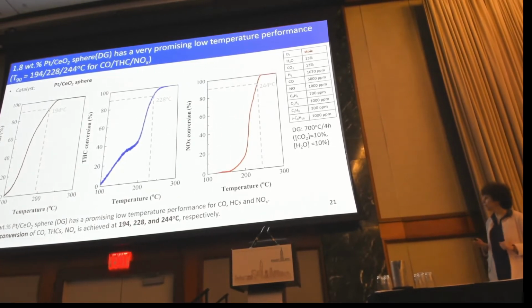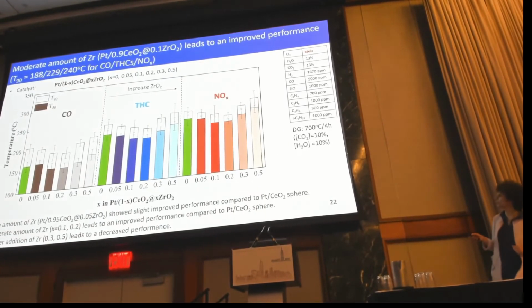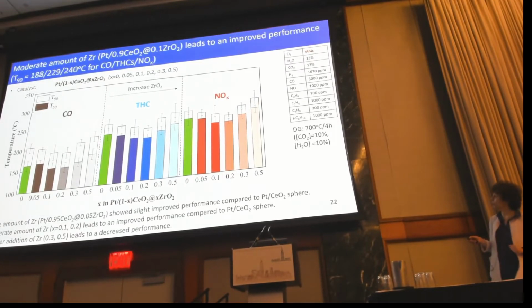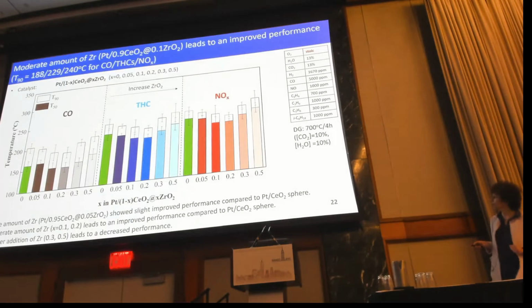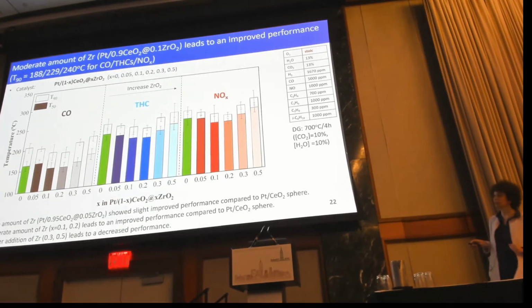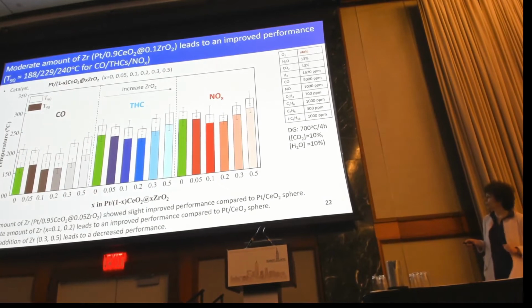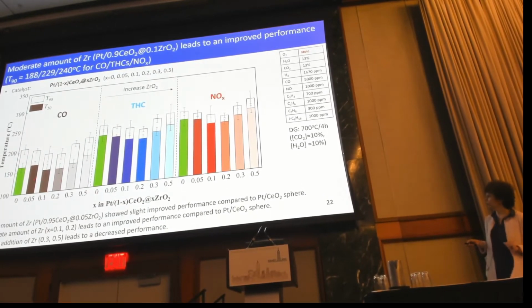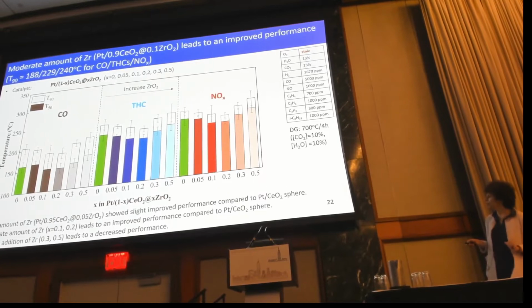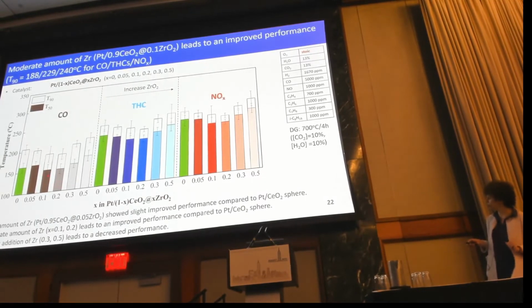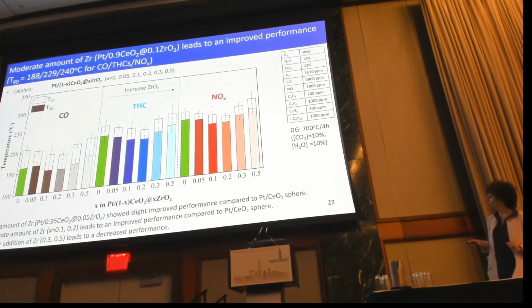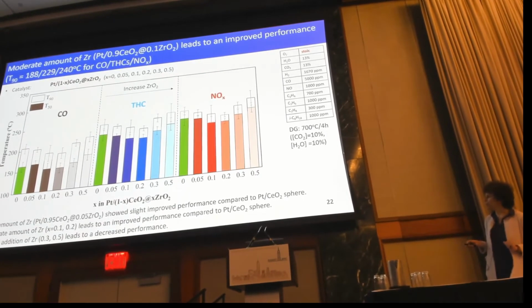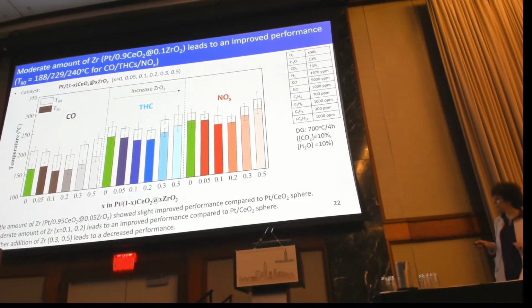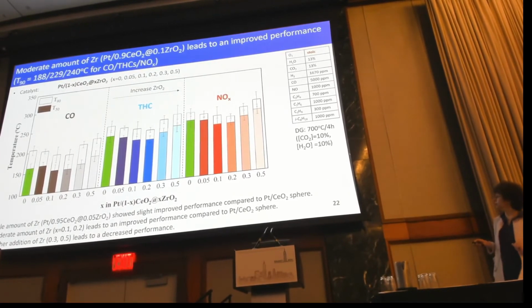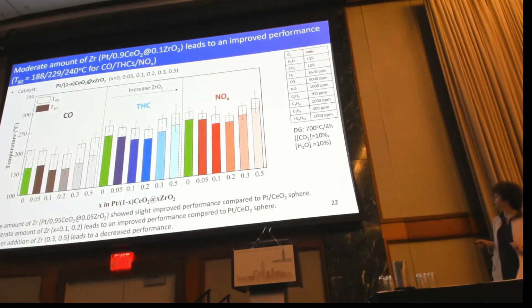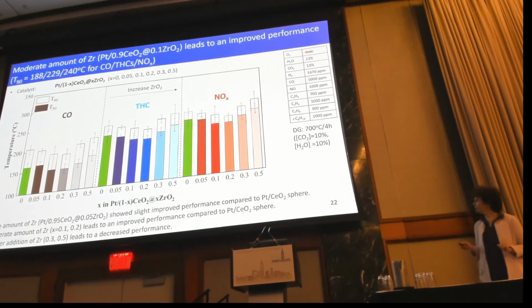Okay, so we decided to start adding zirconium to the sample, and here you can see the bar chart of the temperature at which 50% and 90% conversion is achieved. From left to right, we increase the zirconium content. The green bar here is the ceria spheres without zirconium. We see that by adding zirconium, we see some improvement in the performance up to 0.1 and 0.2 molar concentration of zirconium. But when we start adding more zirconium to the sample, we see that the catalyst slowly deactivates. And this is the same for CO, hydrocarbons and NOx. So this is the performance after degreening.